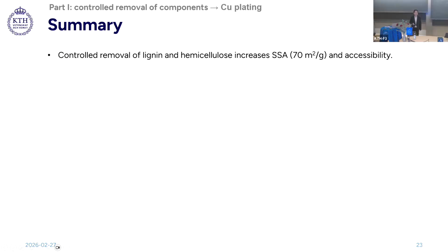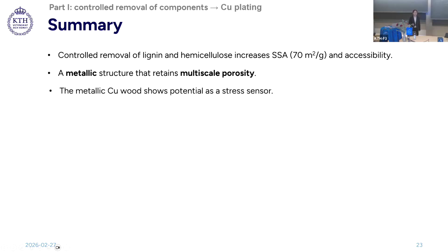In summary, here we demonstrate that the controlled removal of lignin and hemicellulose is an effective cell engineering strategy, which increases the specific surface area to 70 square meters per gram. With the help of cell nanoengineering and the subsequent electroless copper plating, a metallic structure that retains the multi-scale porosity can be achieved. The resulting metallic copper wood shows great potential as a stress sensor.